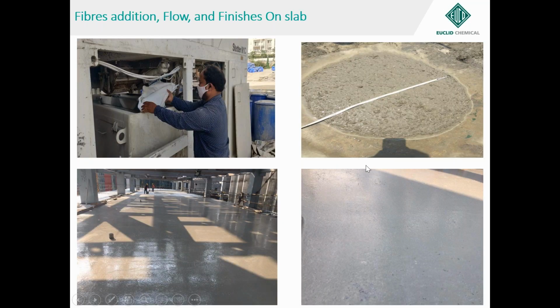Again, as I said, for self-compacting concrete, there is no compromise on flow, and curing cannot be compromised. A lot of people ask why, when I'm adding fibers, I should really do curing. It is to avoid shrinkage, so please do not compromise on that. Here you also see one of the engineers adding the fibers into the dry mix in the bin directly because they did not have a fiber dispenser.